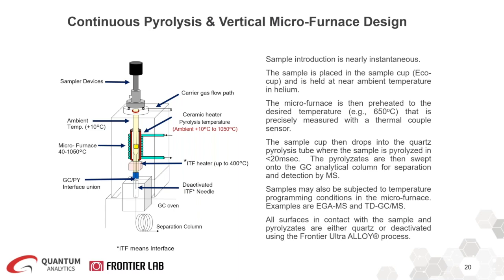So as we mentioned, this technology is really based on a continuous mode analysis, where your sample is held at an ambient temperature while the furnace is preheated. So the sample does not get exposed to any heat prior to the analysis. As a result, there won't be any degradation or evaporation of the lighter components prior to the analysis.